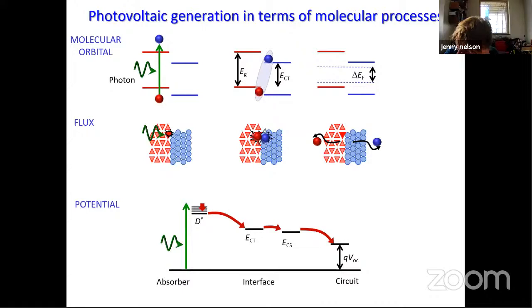I think my reaction to that is I wish I knew. We're at time scales and length scales where we may have a coherent excitonic process going on. And there are systems nowadays where this excitonic state and the CT state are close enough in energy that they have effectively hybridized. If you look at the structure of those electronic states, you could see something which is not quite an exciton, not quite a charge transfer state. For those systems, it's very likely that you have some state which is, as you say, jumping backwards and forwards between the two, some hybrid state which evolves over time to be mainly charge separated from having been mainly excitonic.